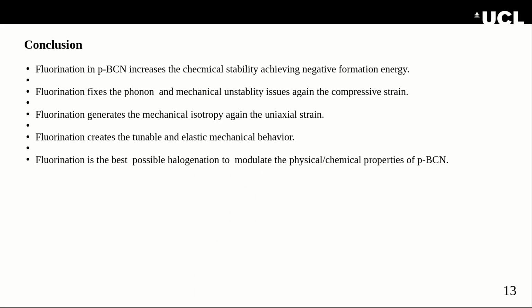Okay, the conclusion. We conclude that fluorination in penta-BCN increases the chemical stability and helps to achieve negative formation energy, and it also fixes the phonon instability and the mechanical instability under compressive strain. It also enhances the mechanical isotropy, and it can be used to tune the elastic behavior over a different range. And we can conclude that fluorination is the best possible way to tune the properties of pentagonal BCN.